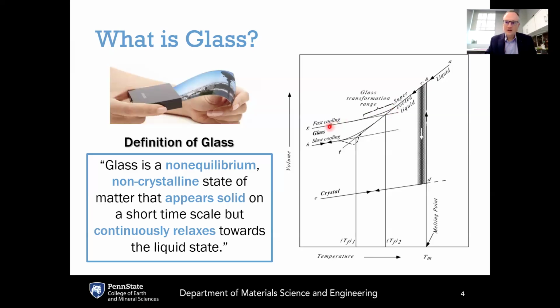Now, is the glass equilibrium or even metastable equilibrium? No, it's not. Glass is a non-equilibrium state of matter that is continuously trying to relax back to its metastable equilibrium, which is the supercooled liquid. So the only reason that we observe glass at all is because we are catching it kind of frozen in time. We are observing it on a time scale that is too short for it to flow. But if you either wait a long enough period of time, or if you take a glass and you heat it up into this glass transition regime, then you're going to allow the atoms in the glass to flow and to go back to its metastable supercooled liquid phase. So the glass and the supercooled liquid are connected via this glass transition regime.